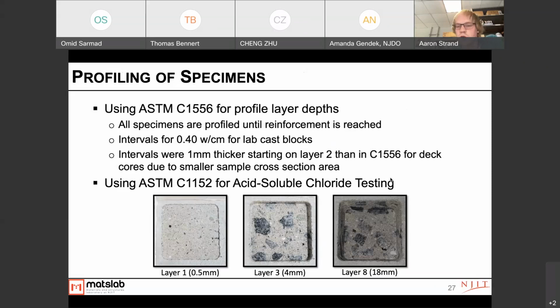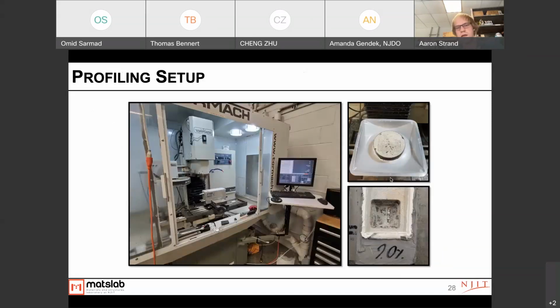And then we did acid-soluble chloride testing using ASTM C1152 to determine the chloride content. This is what our profiling setup looked like. We used a Tormach CNC machine.